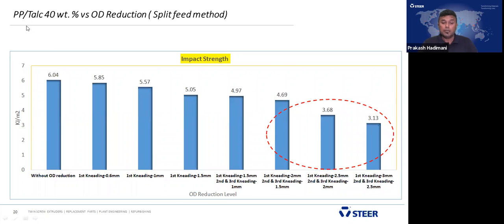Now we are coming to the polypropylene talc impact strength. Even in the impact, up to the first kneading at 1.5 millimeter and the second and third kneading at 1 millimeter reduction, there is not much change in the impact strength. The impact strength started reducing after the first, second and third kneading. The first kneading at 2 millimeter means 1 millimeter per side, and the second and third kneading at 1.5 millimeter means 0.75 per side. That is a slight reduction in the impact strength, though the impact strength is mostly maintained. In the case of the first kneading at 3 millimeter, meaning 1.5 per side, the second and third kneading show 2.5 millimeter for both sides.